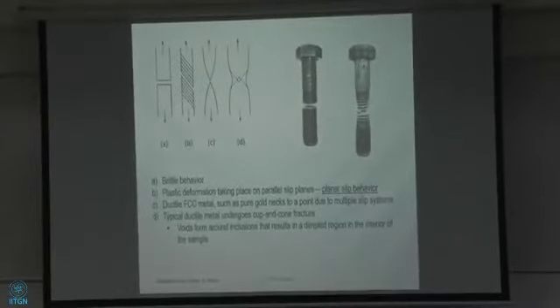Oh, yeah. I'm actually seeing here two pictures. It's a very simple thing. There is your brittle behavior, right? There's no necking, nothing, flat surfaces, the thing broke essentially, right? Here, there is your deformation on a single slip plane system, not single slip plane, single slip plane system. Because if it is a face-centered cubic system, it is the 111 slip plane, right?